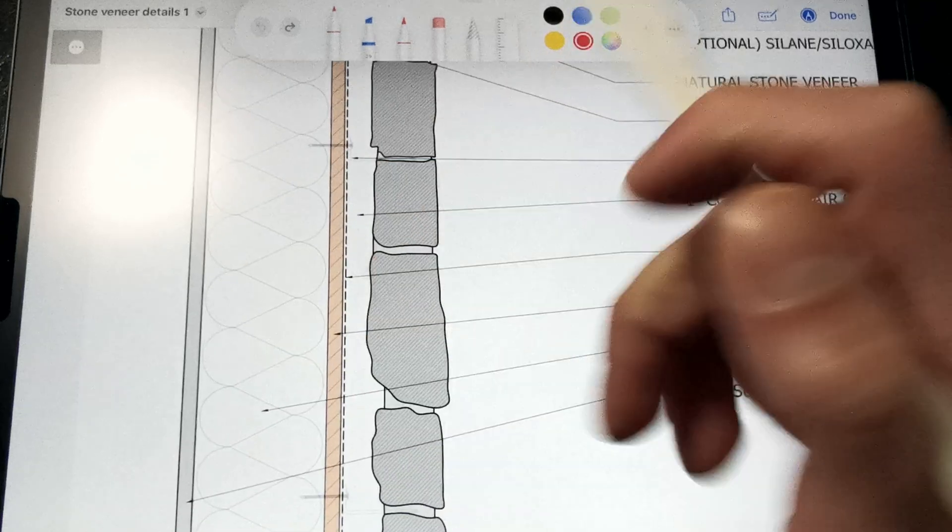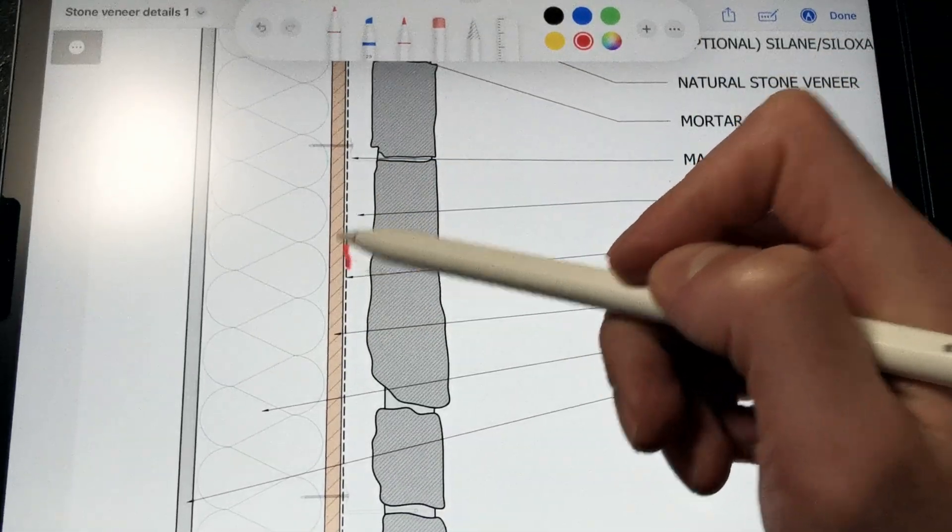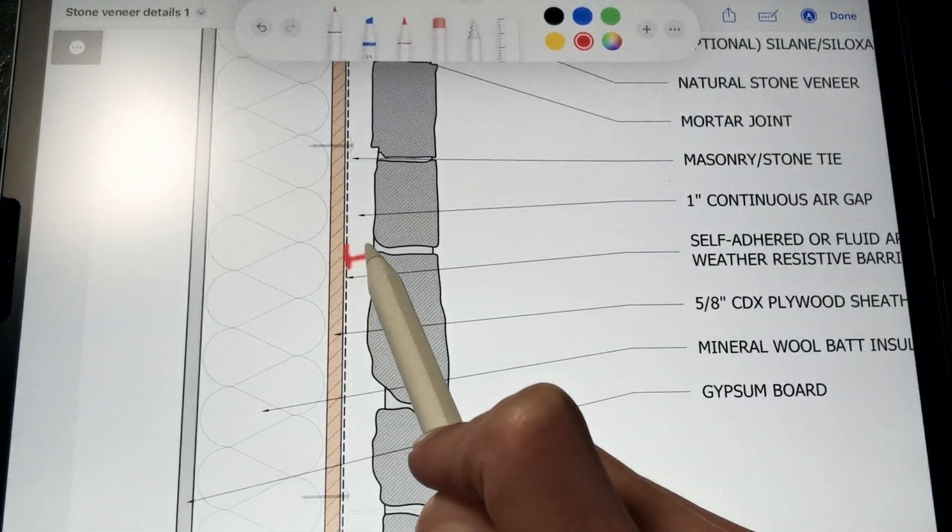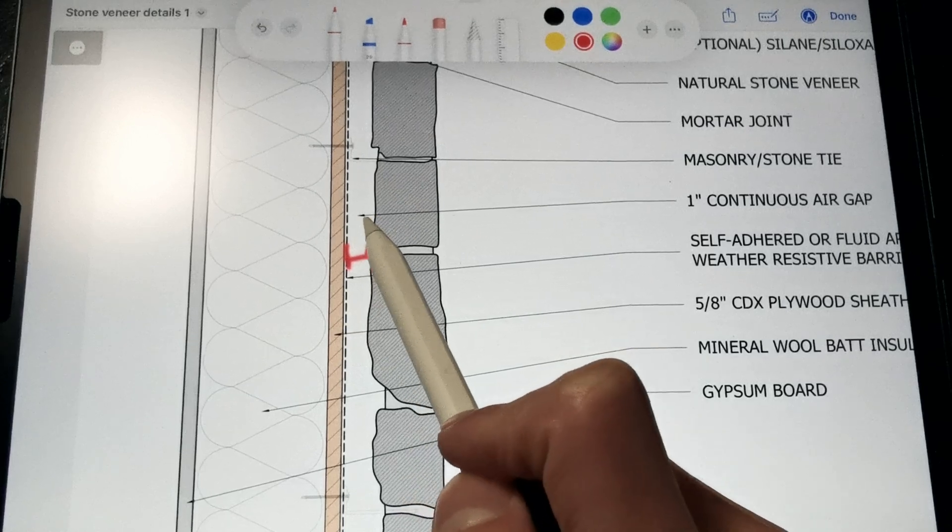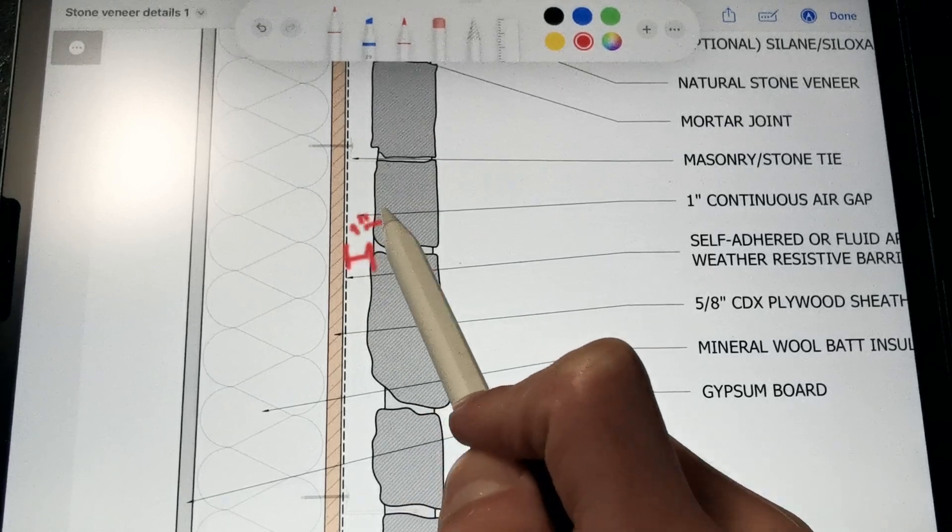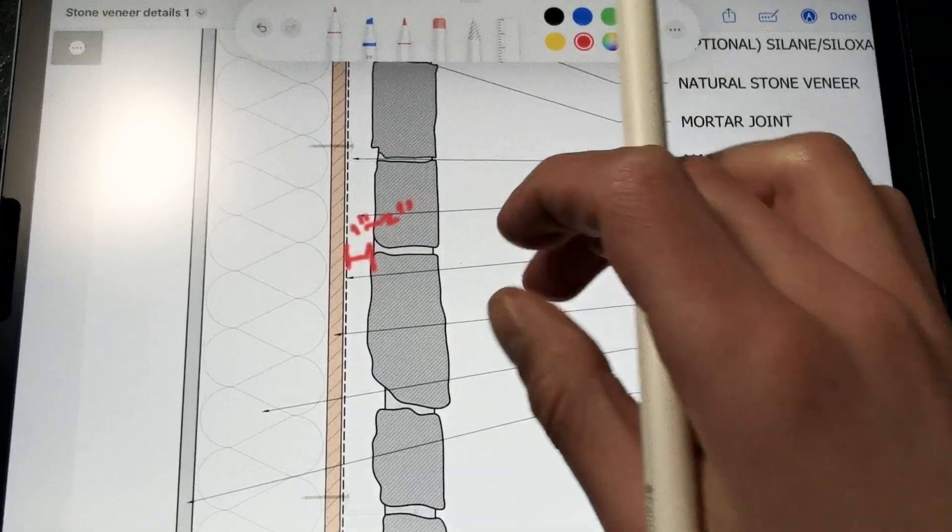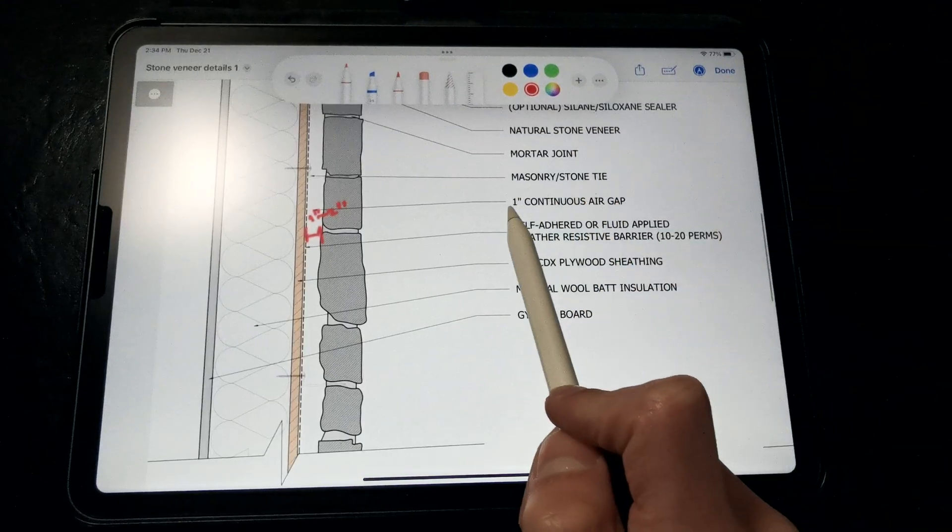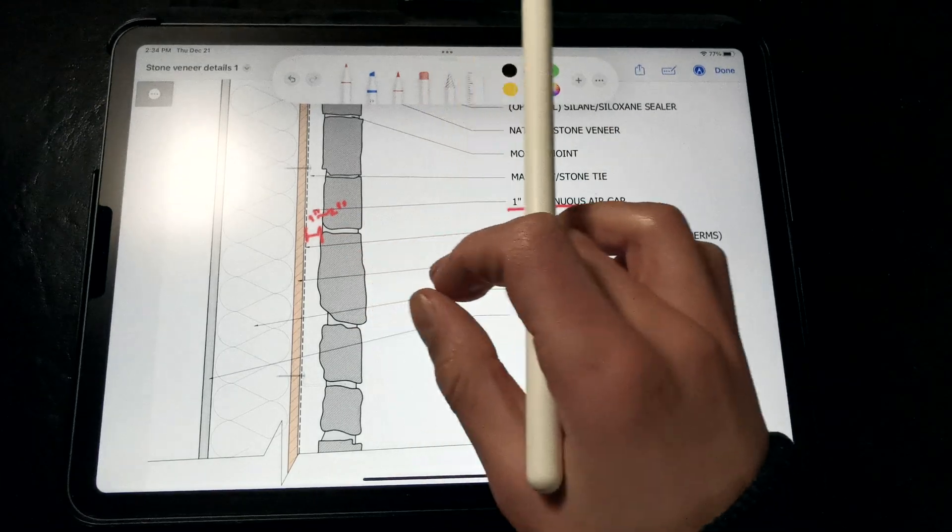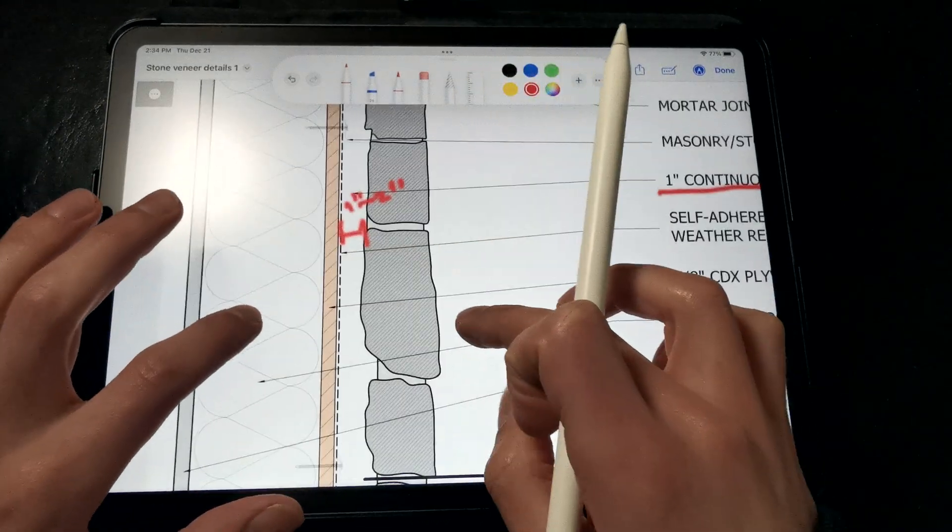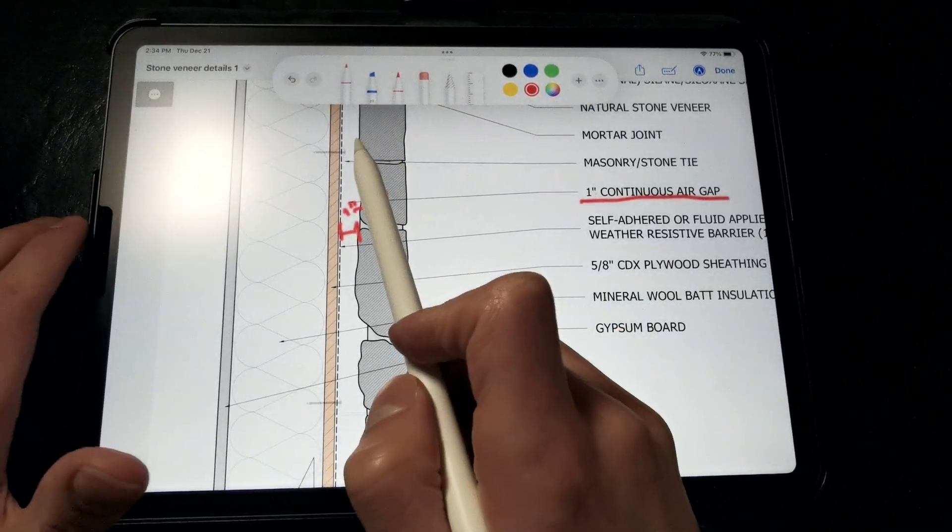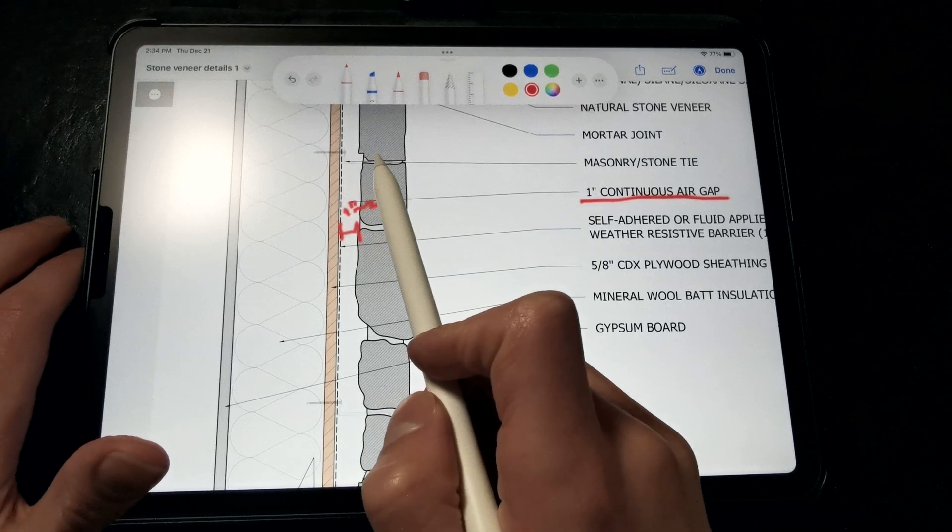To control bulk water, we already have an air gap right here between the surface of the weather-resistive barrier and the actual stone veneer. So that gap is between one to two inches, and that's more than enough to break capillary continuity between the wet stone veneer and the framed walls, even with the stone ties, so we don't have to worry about liquid water actually bridging between the wet stone veneer and migrating through the WRB if we have that air gap.